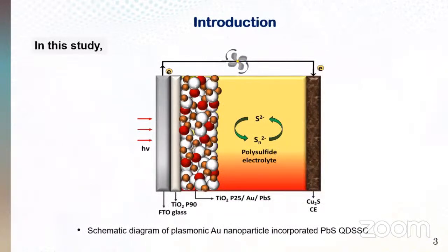QDSSCs are a popular study area in third generation of solar cells due to their low production cost and the excellent properties of quantum dots, such as ability of multiple exciton generation, tunable energy gap due to the quantum confinement effect, and high molar extinction coefficients. QDSSCs have three basic components: photoanode, counter electrode, and electrolyte, as shown in this schematic diagram. In this study, TiO2 photoanode-based lead sulfide QDSSCs have been fabricated with polysulfide electrolyte and a copper sulfide counter electrode.